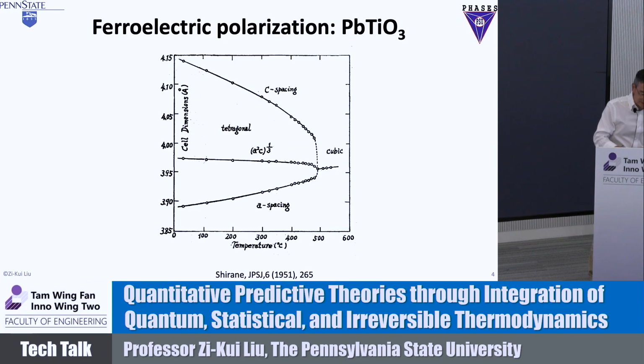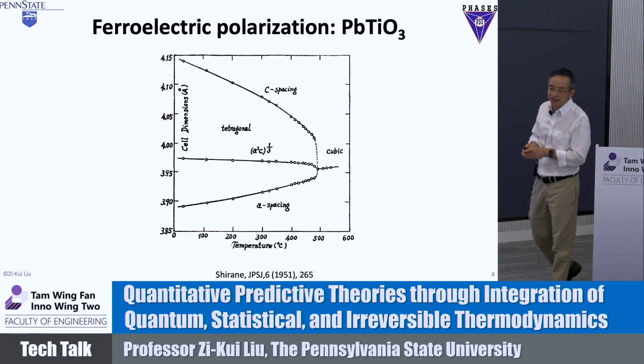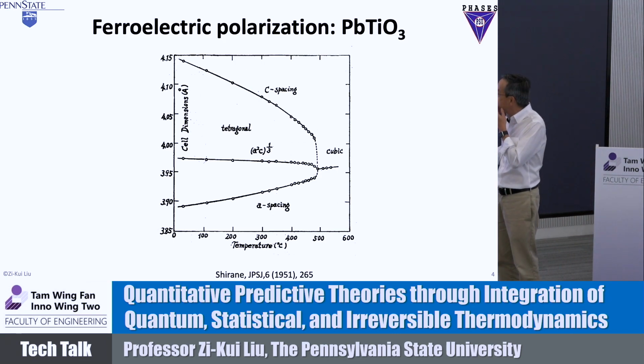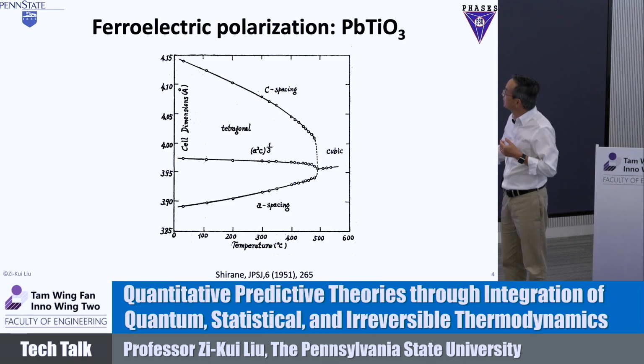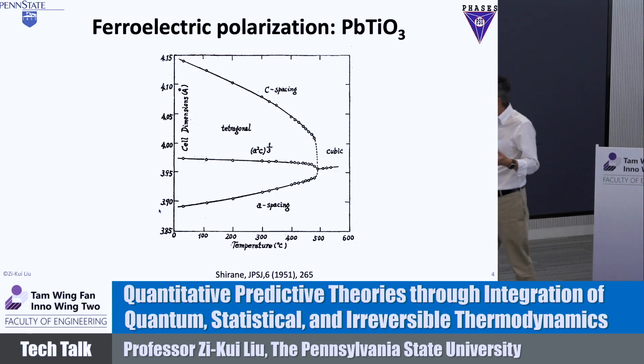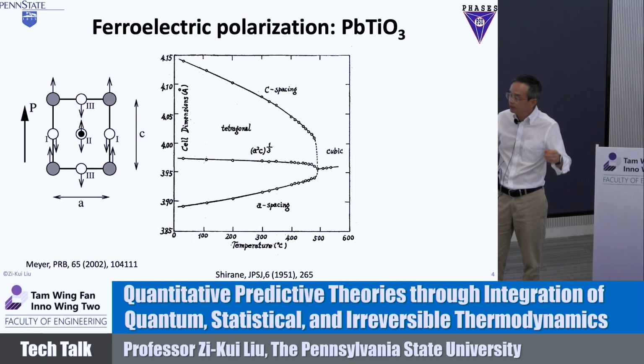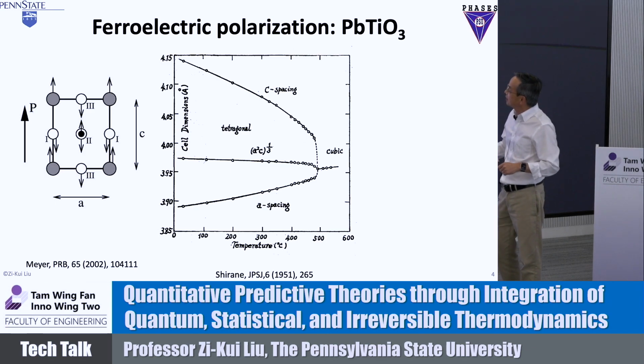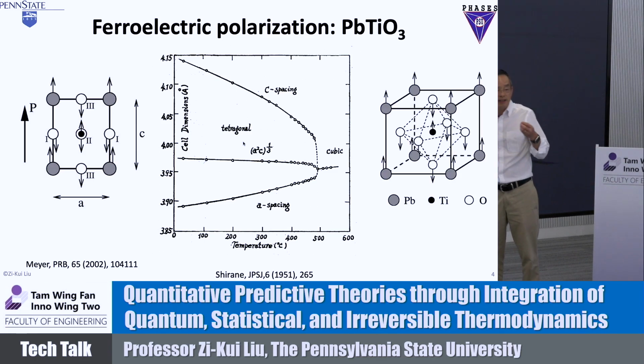The third question I have is about ferroelectric material. Again, this is lead titanate, the classical one. At a low temperature, you see that you have a c/a ratio, so it's tetragonally polarized. Okay, so you get the structure, and the center atom, the titanium atom in the middle, is going to move, right? Get displaced. Then you say, okay, if you increase the temperature and continue the X-ray, you finally get a cubic. Then you find the cubic, and the titanium in the middle.